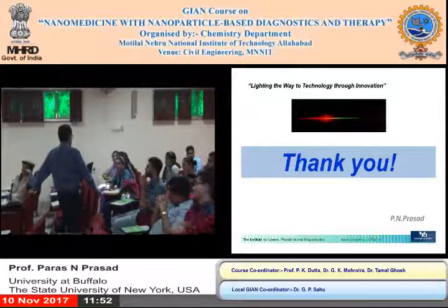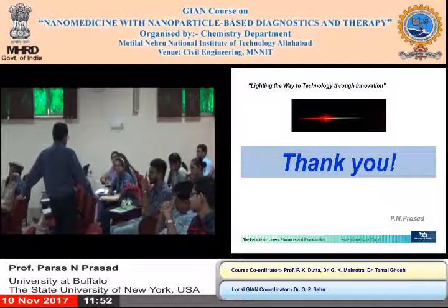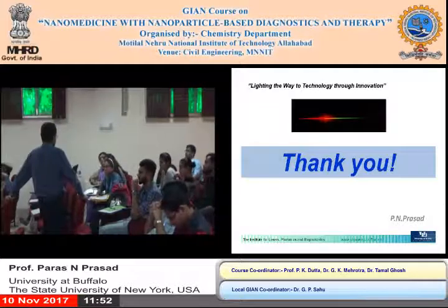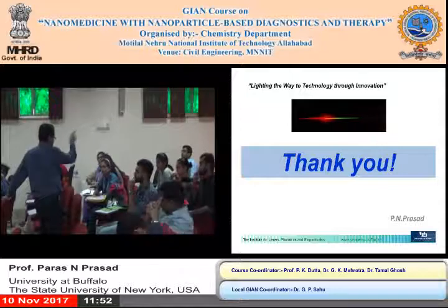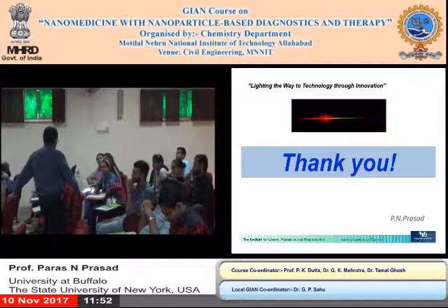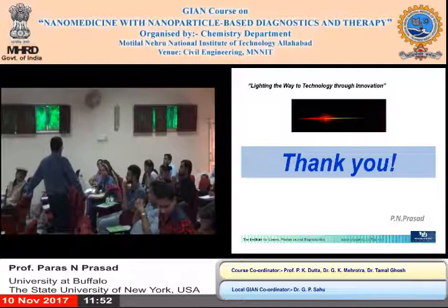You just don't use a lanthanide; you use it for a specific property, like gadolinium. We use it for MRI. Gadolinium we also choose for radiotherapy because it absorbs X-rays and generates secondary effects. And if you use erbium, I use erbium for emission. It takes the IR and converts it into different wavelengths, right? Or thulium. So you use the appropriate lanthanides for the property. Similarly with actinides, you need to choose which actinide you want to use and what property of the actinide you want to use.